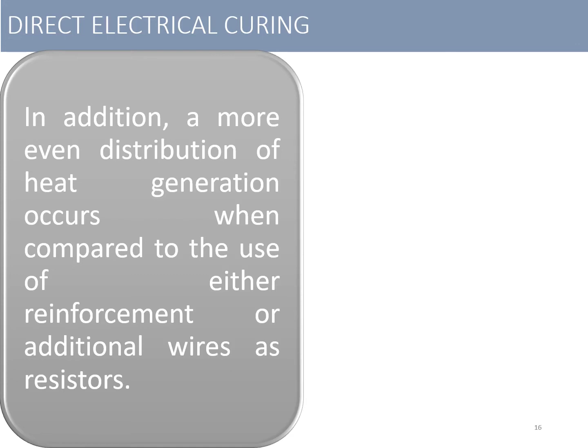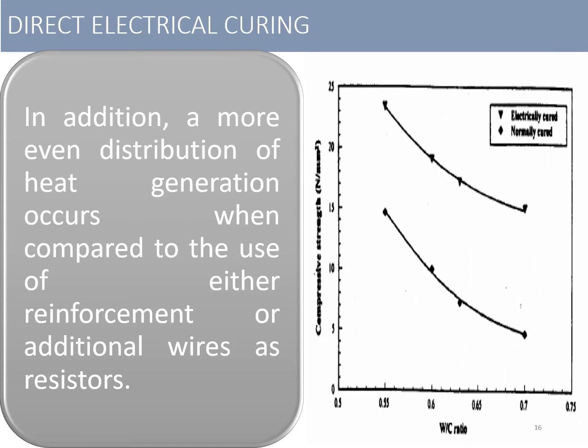If you see the graph plotted between the water cement ratio and the compressive strength, you can see that there are two lines being plotted. One is for the normally cured concrete and the second is for the electrically cured concrete. You can say that as compared to the normally cured concrete, the compressive strength is much higher in the case of electrically cured concrete, even though the water cement ratio has gone beyond 0.55 up to 0.7.